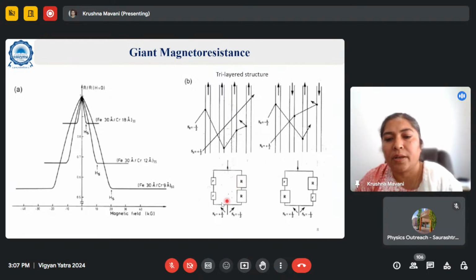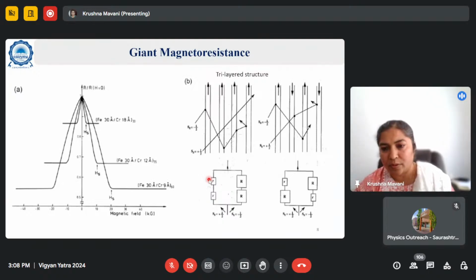Here you have larger R, okay, and then this spin, if it is negative, it will have more scattering at the interface. It will have more resistance, right? Another channel which is operative only for spin up will have lower resistance value. Similarly, this can happen if it is anti-ferromagnetic alignment. The scattering can take place at interface for both the types of spin alignment, right? Which can be understood using this kind of diagram where you have a combination of larger and smaller.